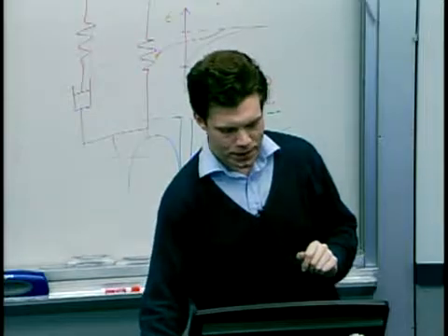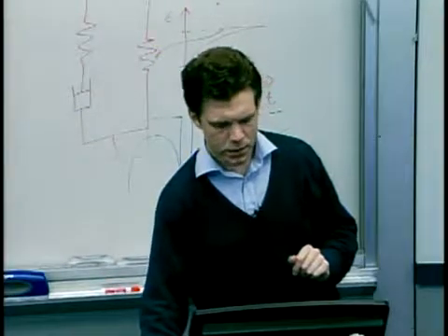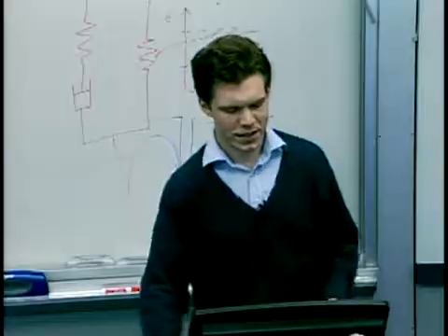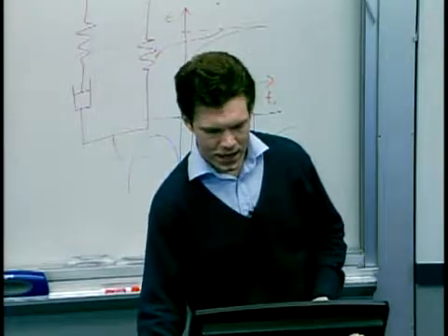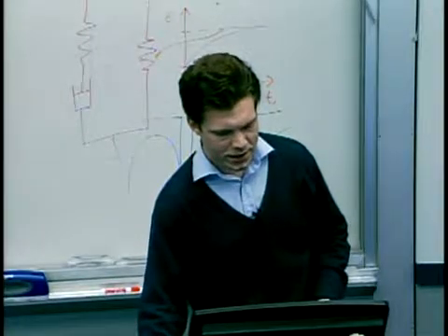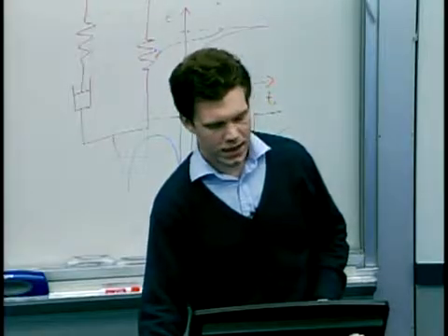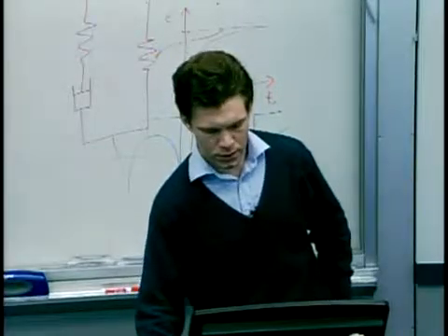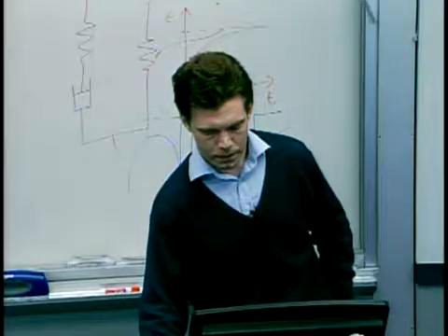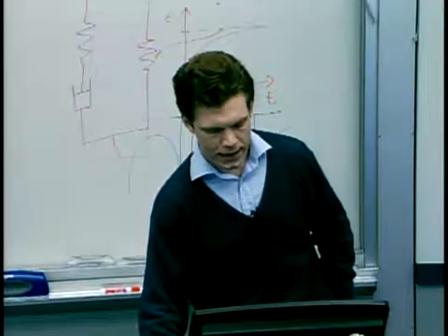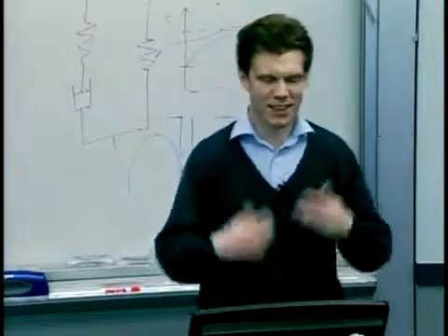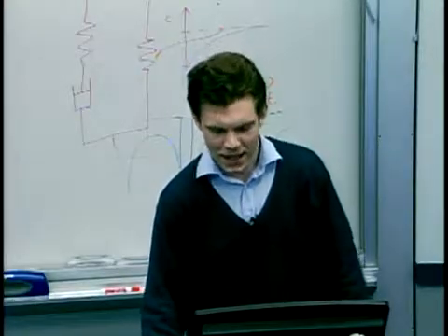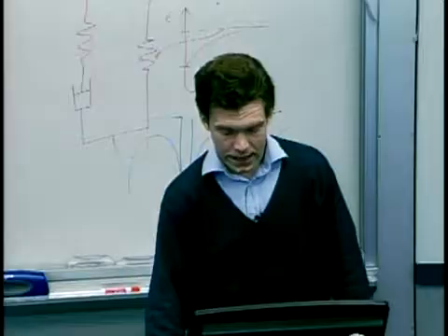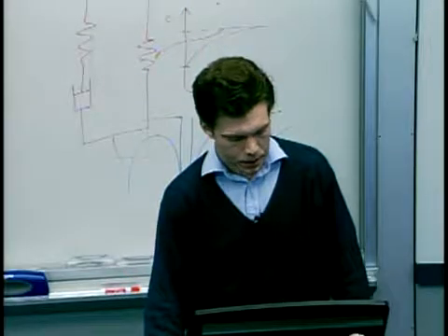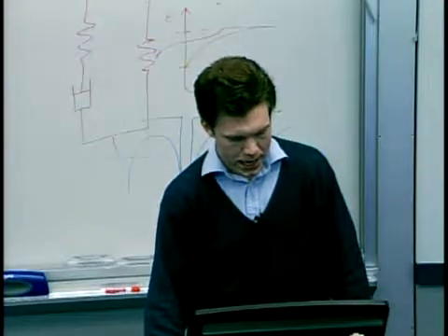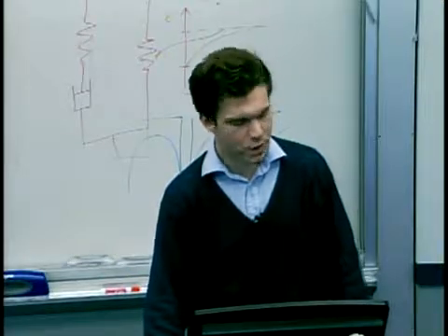So anyway, interspersed center point runs, and then what we've done to provide some basis for a test of significance of the effects is to take the average of these peak penetrations. So we've just taken the mean over all feature sizes and orientations and everything, and put it down here. And so you can do an ANOVA, and you can look at the significance of various effects, and actually, we get the impression that certainly temperature and force and hold time are significant.